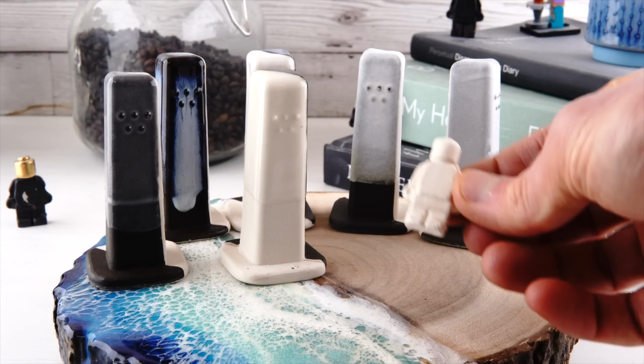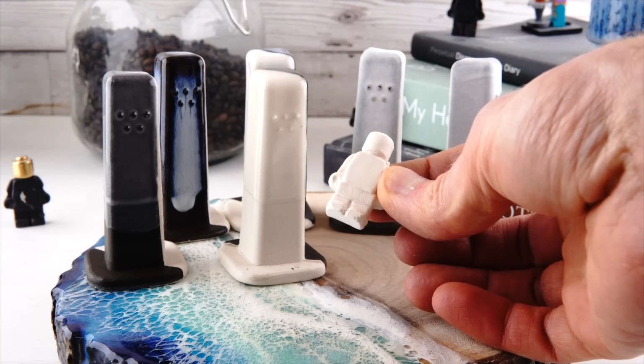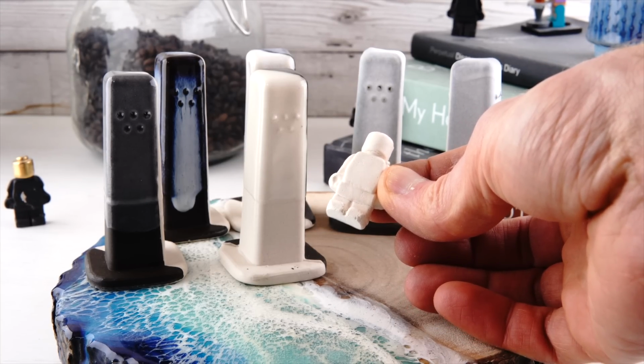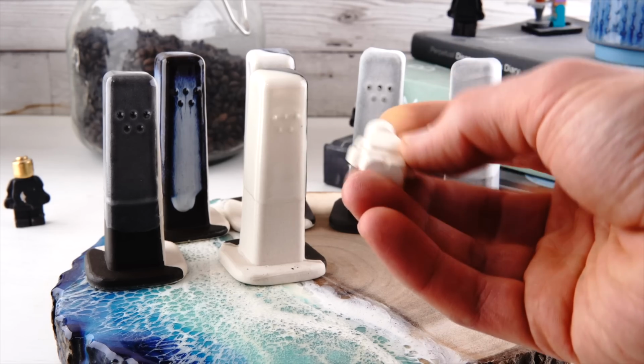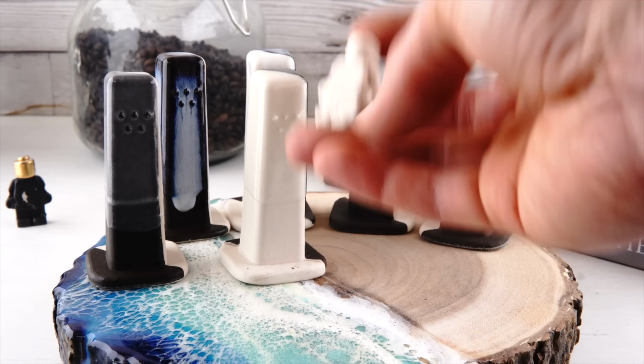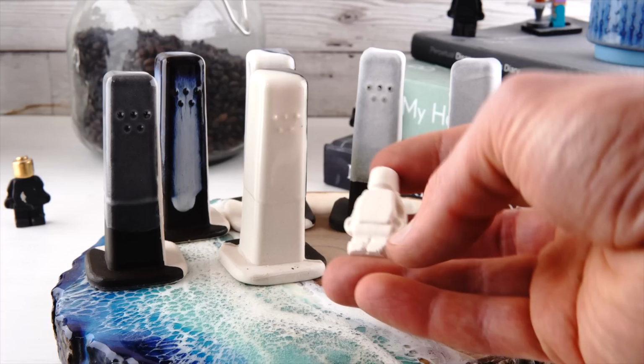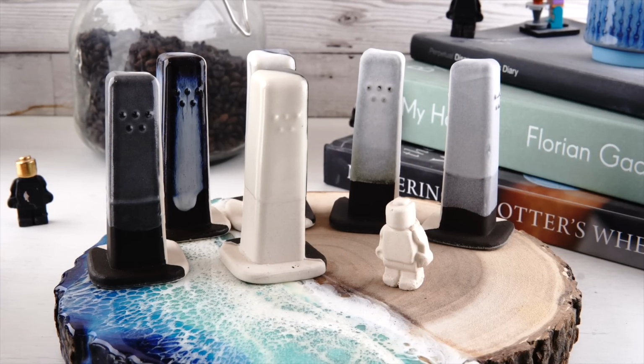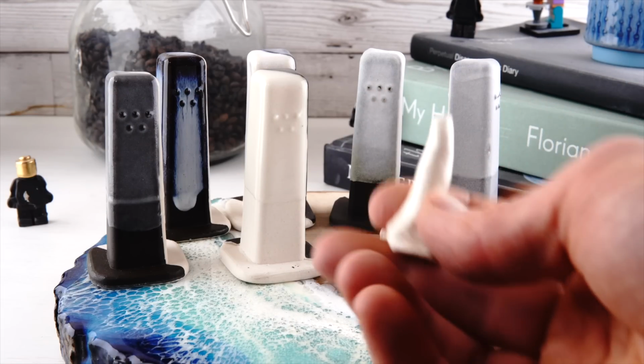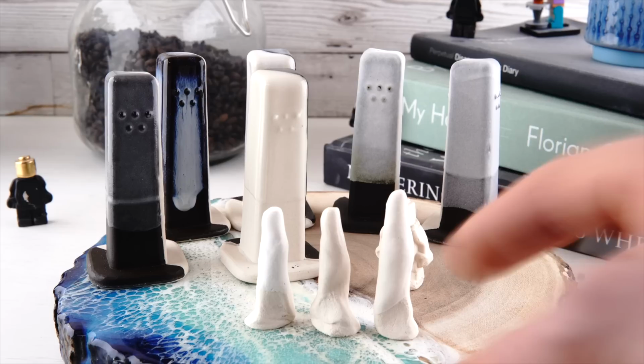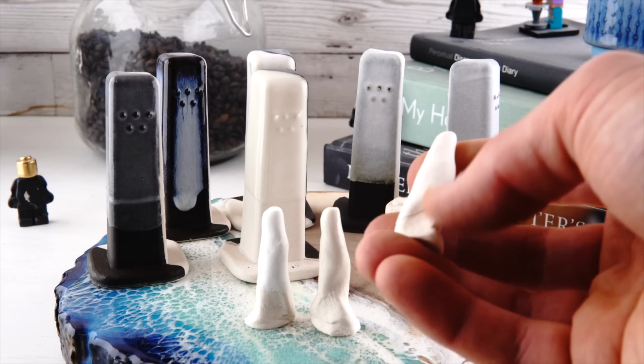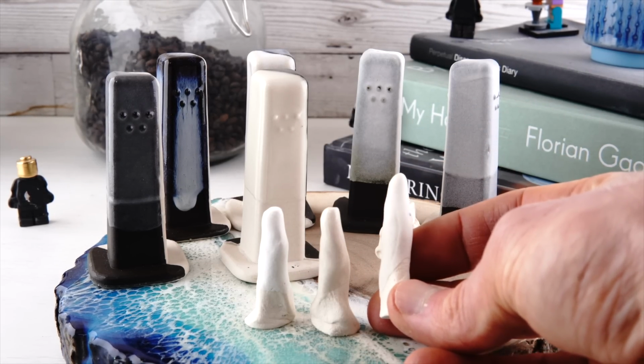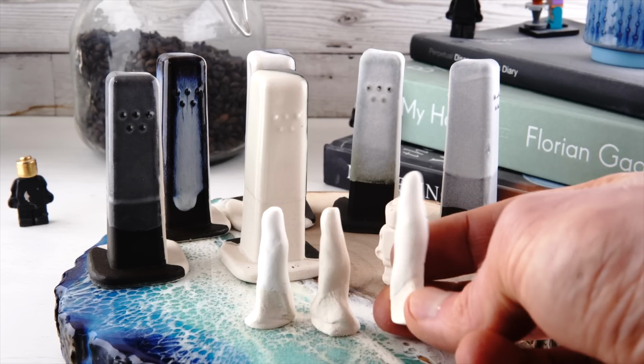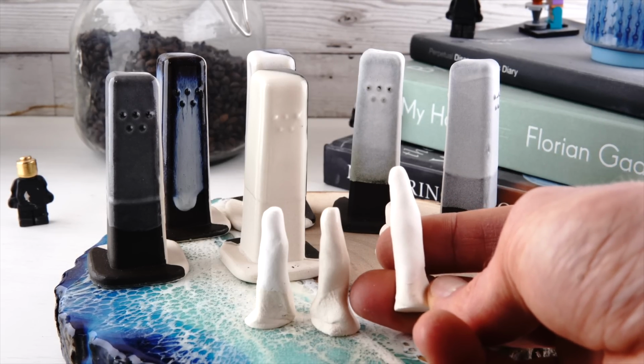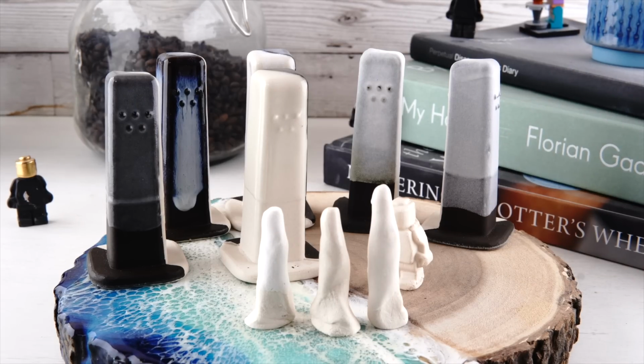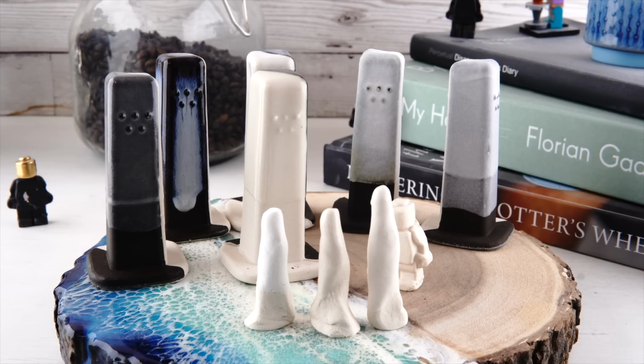And then at the most extreme we have this. This minifig is made using what ChatGPT said would be a glossy cone 6 glaze. It actually is an underfired clay. There wasn't enough fluxing power in it to vitrify the clay even, but that's a clay body, that's not a glaze. And I used the remaining clay to make other little test tiles. So these ones have a completely underfired glaze on a completely underfired clay, both of which ChatGPT thought would be a glossy cone 6 glaze. So the results are as we would have guessed from the chemistry, and not at all what ChatGPT said they were going to be.